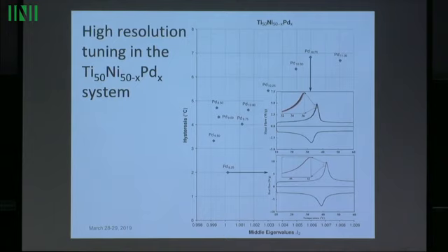So this is back and forth, heating and cooling and measuring the latent heat, essentially. This is the heat flowing into the specimen, the rate of heat flow into the specimen. And if you look closely, there's a migration of the transformation here. And this is lost when you make even one of these high resolution changes from 10.75 to 9.25.